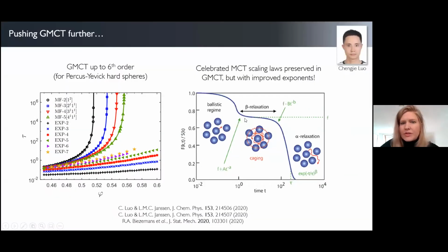So the exponents I'm referring to: if you take your microscopic dynamics, your intermediate scattering function somewhere close to the glass transition, and you measure the onset of this plateau, how that scales in time, the decay away from the plateau, and the long-term decay here, there are certain exponents a, b, and there's also a gamma that relates to the power law for the alpha relaxation time. You can fit those from your simulation. And that's just a number, it's different for each material you're thinking about.